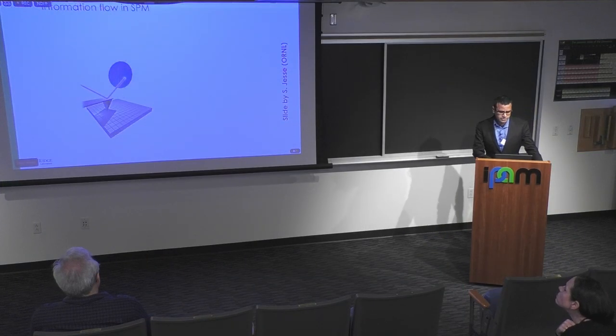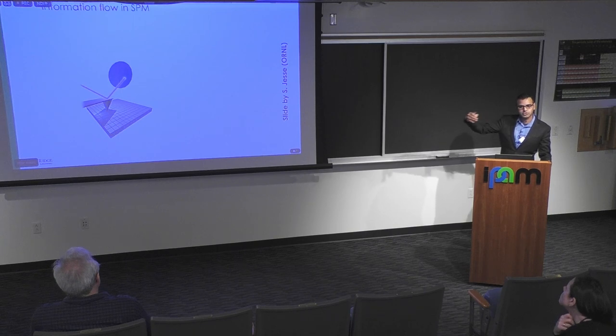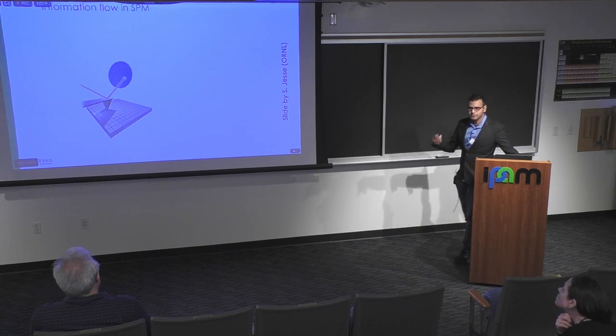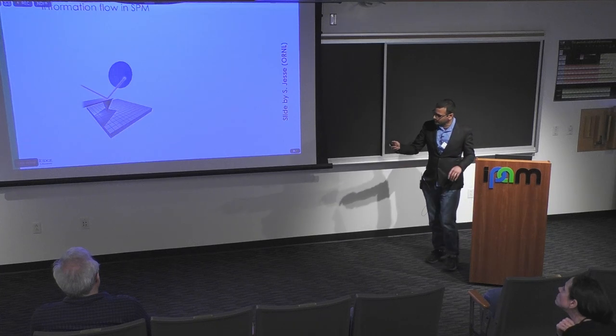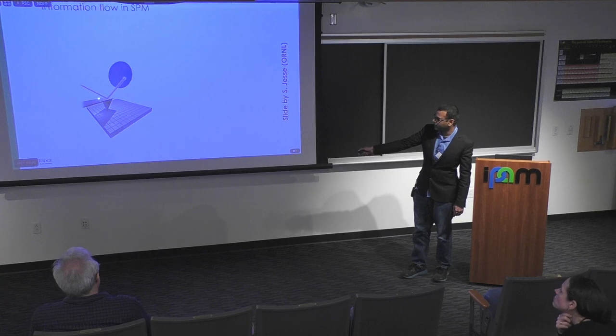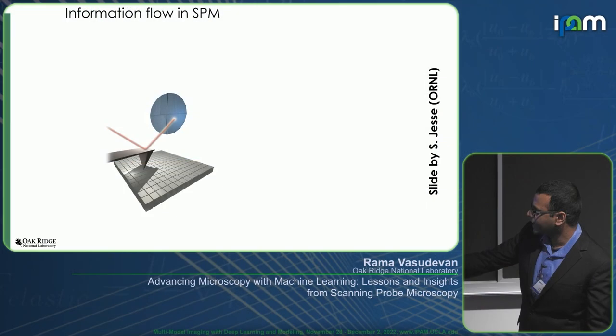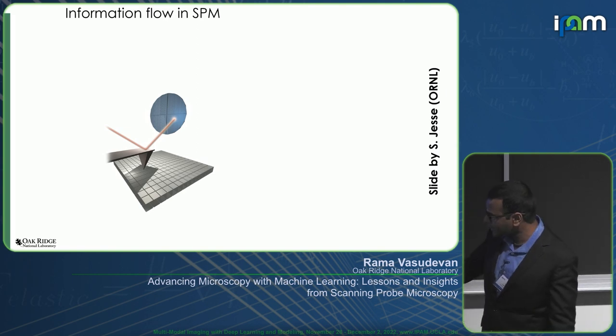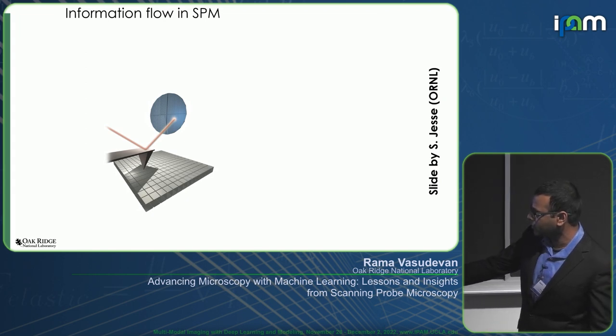So the tool that I'm going to talk about today is really the scanning probe microscope. I know not everyone here is familiar, because most of the people here are probably familiar with traditional imaging like electron microscopy. But a scanning probe microscope is also a type of microscopy, and it images in a slightly different way. The way that it images is that we have a very small cantilever, a few hundred microns, and at the end of this cantilever we have a very sharp tip, a probe. This probe typically has a radius of around 10 nanometers. We take this cantilever and we scan it over the surface. As we scan over the surface, we bounce a laser off the back of this cantilever onto a four-quadrant photodetector. As the cantilever wobbles up and down, we can measure the deflections on this photodetector to give us a readout of the topographic information that's present in our sample.